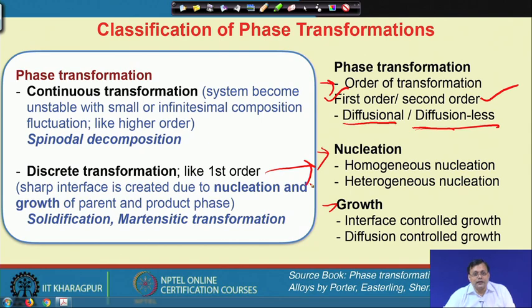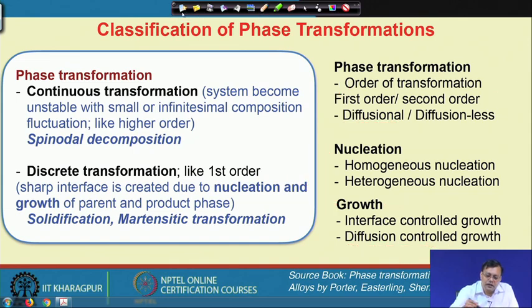So, if you like to solidify a liquid in a mold, then heterogeneous nucleation will start at the interface between the mold wall and the liquid. So, that is the case. However, this growth could also be interface controlled or let us say a diffusion controlled growth. So, let us say a product phase, if it has to grow in a parent matrix, then diffusion of atoms may be required. So, that growth is mostly controlled by diffusion, and if it is like a Martensitic type of transformation where no long range diffusion is required, then only the interface moves. Okay. Interface moves and it completely covers the whole parent phase, it becomes interface controlled, and there are many other examples of such cases. So, we can also classify or we will try to identify a phase transformation process in these particular aspects.